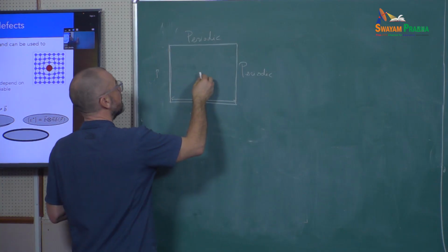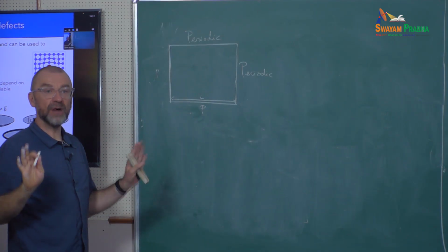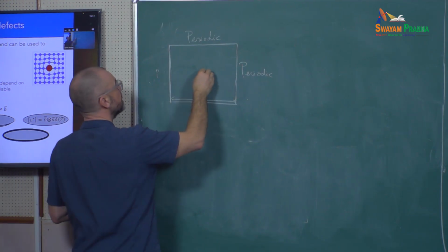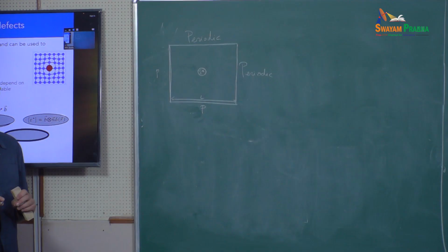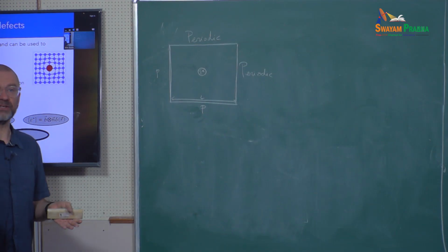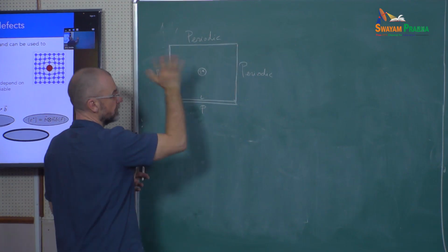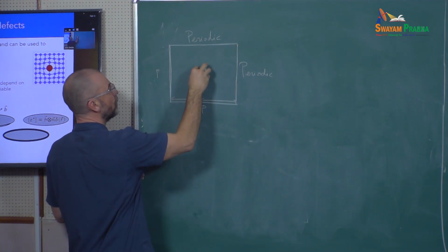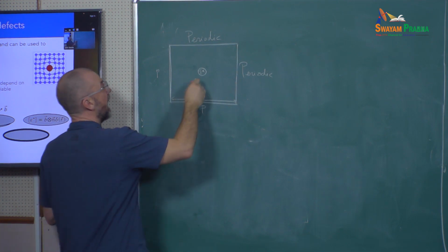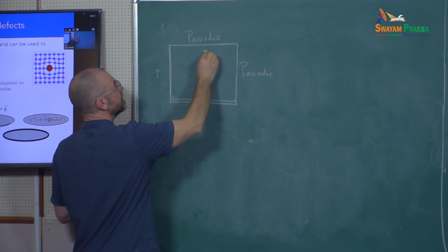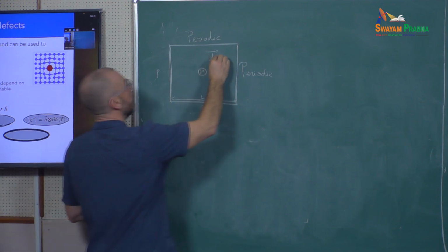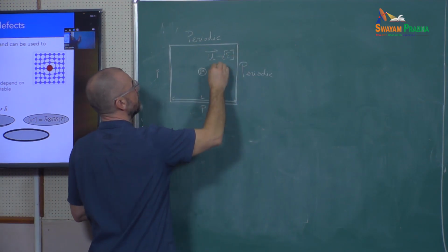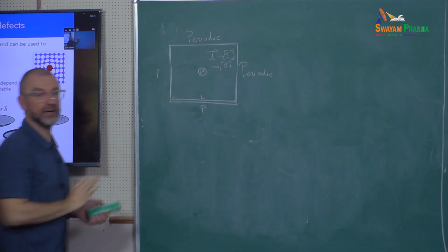Initially I have zero eigenstrains. Now I assume that inside that domain there is a region where I have a non-zero eigenstrain, and I re-relax the system. Initially I had zero displacements. It was my reference configuration. I create some eigenstrain somewhere and relax the system, so now I have a displacement field inside the region. From the displacement field, I know that I have deformations and I have stresses everywhere.